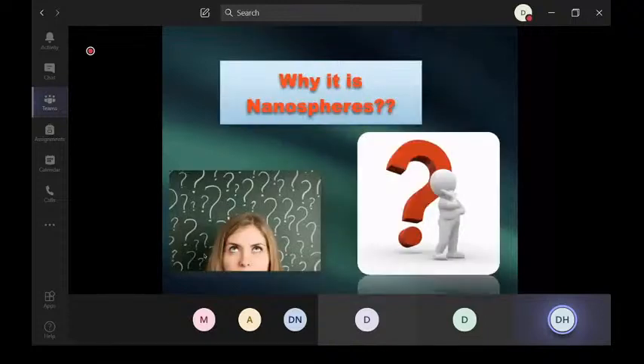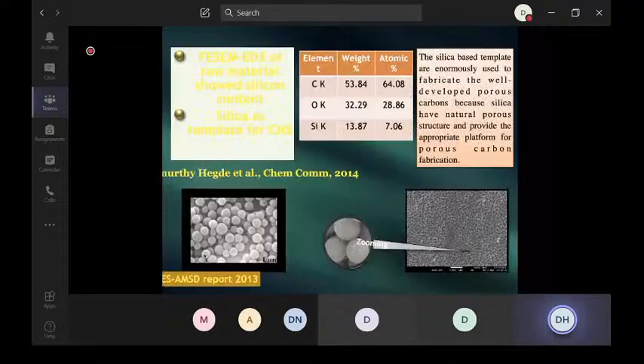So then the question is, we have to explain, because we synthesized the nanoparticle, we proved that they are nano in nature, we proved that they are spherical in nature. The question is why they are exhibiting nanospheres, because anybody can take bio-waste material and synthesize. But most of the editors of high impact factor journals will ask the reason, how you are telling that your material is nanospheres. So then we did some silica based studies, because we wanted to know why we are getting nanospheres. Then we found that our synthesis method is a soft template method.